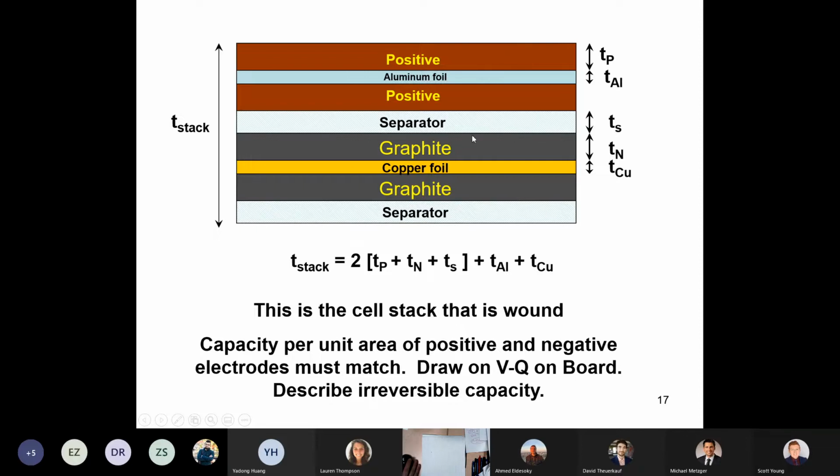And what you want to do is then design a negative electrode that's balanced, meaning it will have the appropriate capacity to accommodate all the lithium that comes from the positive over to the graphite. That's the idea here. And that graphite will have a certain thickness based on its porosity, its specific capacity, its binder content, and its carbon black conducting diluent content, okay?